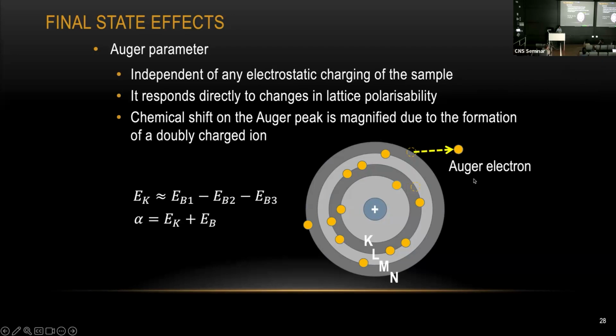Sometimes you can calculate your Auger parameter, which is written as alpha here. That's simply the kinetic energy of this Auger electron plus the binding energy of this electron here. By comparing the Auger parameter, you might be able to compare some chemical difference between your samples. But most of the time, we are not using this parameter for chemical analysis.